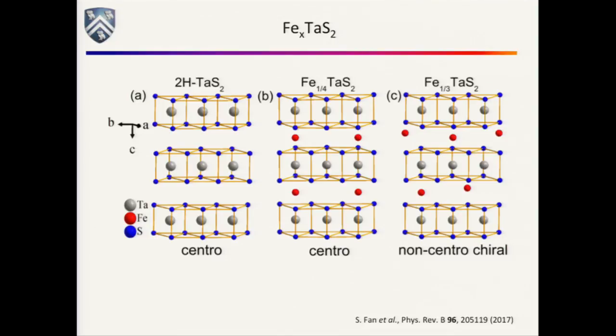And what's interesting is that you can imagine sticking all kinds of stuff between the layers of these TMDs. People do all sorts of things. There are two particular commensurate fillings that are nice, very stable, very well defined: one is iron a quarter tantalum disulfide, and another is iron a third tantalum disulfide. These things are magnetic, they're metallic, and when I say they're magnetic, I mean they're ferromagnetic. And it's local moment ferromagnetism.